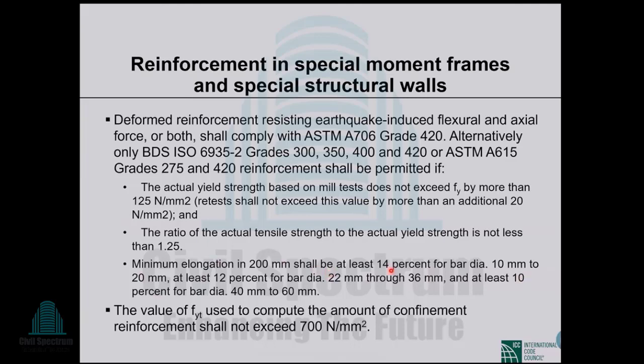So elongation. In BDS ISO there are two limits for elongation. One elongation at fracture and another elongation at the highest force, highest stress. But this is different. This is total elongation for 200 millimeter gauge. In BDS ISO, the gauge is different. The gauge is 5D. Here, it is following ASTM. In ASTM, the gauge length for lower diameter rebar is 200 millimeters. On that gauge length, the elongation must be at least 14%, at least 12% for bar dia 22 millimeter to 36 millimeter, and at least 10% for bar dia 40 millimeter to 60 millimeters. So these are the elongation limits that we have to ensure if we want to use that rebar for special moment frame or special structural walls.